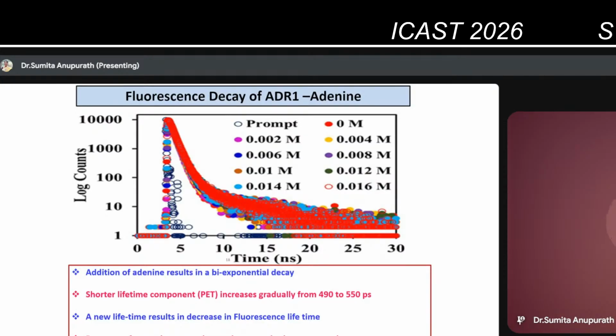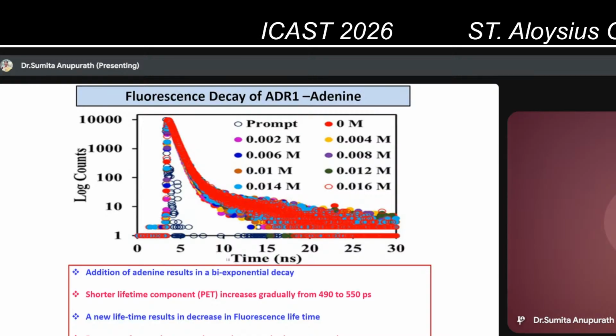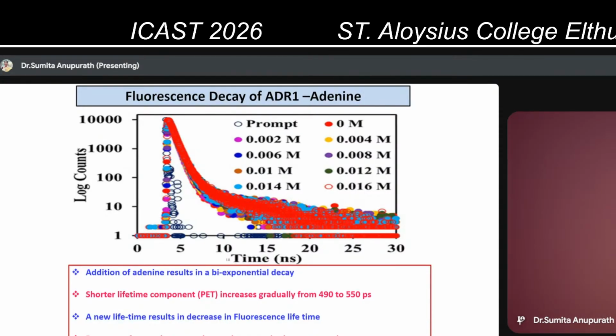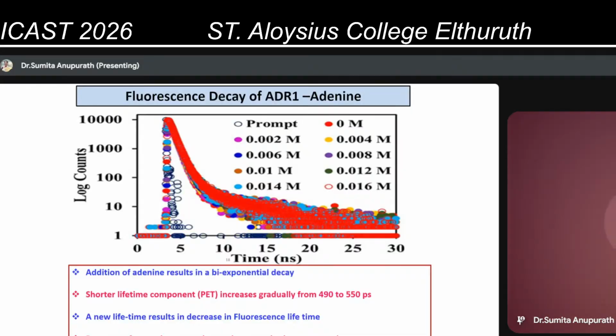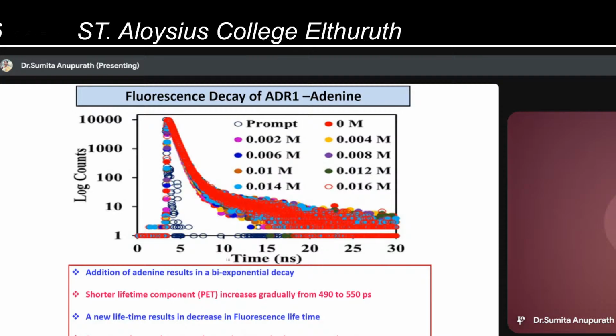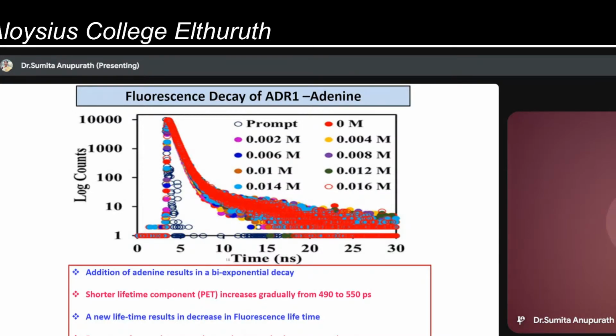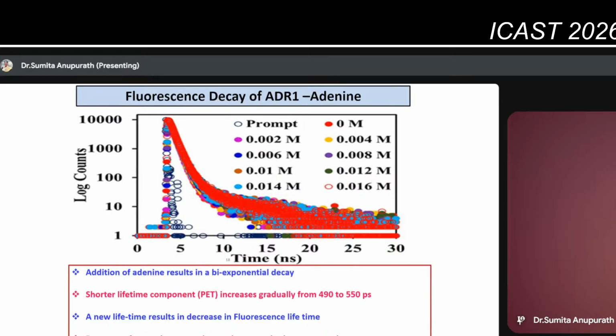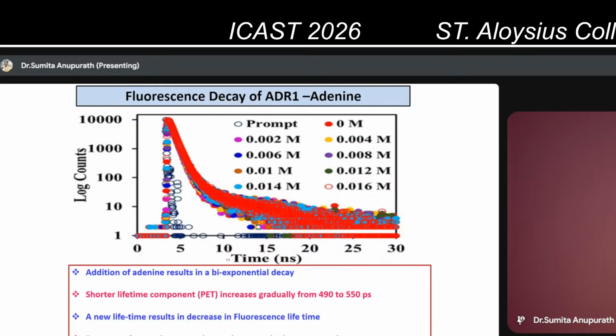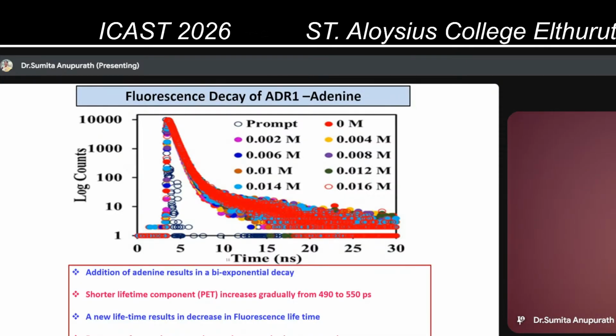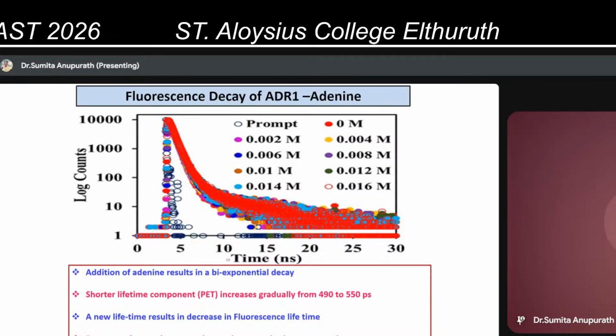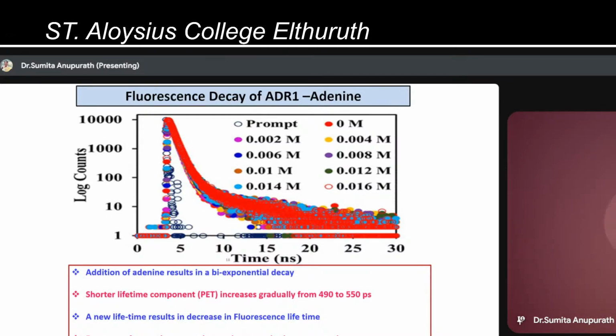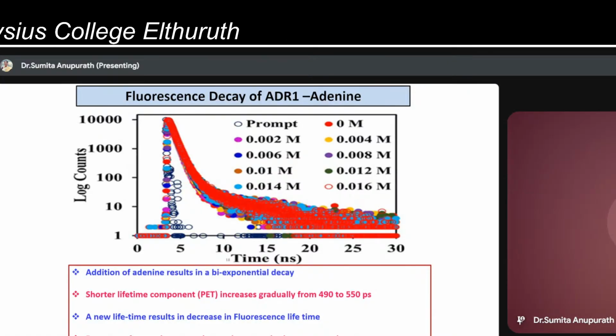Further, we carried out fluorescence decay of the ADR1 dye, and the single exponential decay of the dye changed, or transitioned, into a bi-exponential decay, which shows that the environment around the dye has changed, or you can say that there was the presence of multiple environments in the system. And also the PET component shifted from 490 to 550 picoseconds. The short lifetime shows that PET was gradually suppressed. The data also showed that there was a new lifetime generated, and that is due to the formation of new microenvironments in the system.